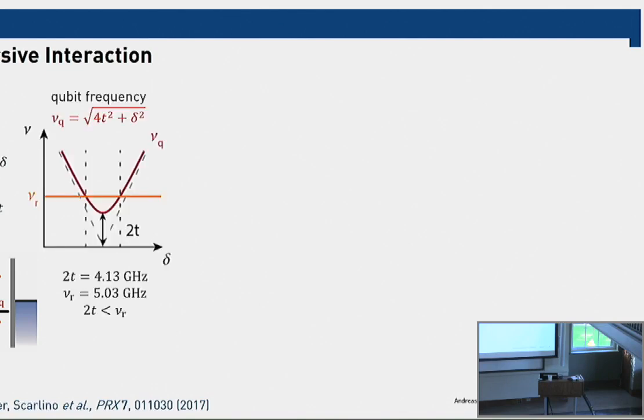And so you can then tune voltages on these gates to bring two of these levels in the vicinity of each other. And if you control the distance between the two dots, you can control the tunnel coupling rate between the two. These two states will then hybridize in bonding and anti-bonding orbitals, so symmetric and anti-symmetric superpositions of having either an electron on the left or one on the right. And this is the energy level diagram versus this detuning parameter, little delta, which is the energy difference between the charge state in the left dot and the charge state in the right dot.